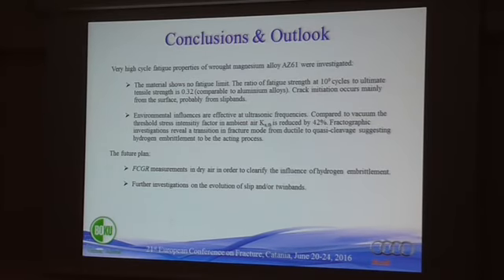So let me now conclude my talk and also give an outlook on the future plan. The very high cycle fatigue properties of wrought magnesium alloy AZ61 were investigated. The material shows no fatigue limit. The ratio of fatigue strength at 10 to the 9 loading cycles to ultimate tensile strength is 0.32, which is comparable to aluminum alloys. Crack initiation occurs mainly from the surface, probably from slip bands. And we could show that environmental influences are effective even at ultrasonic frequencies.